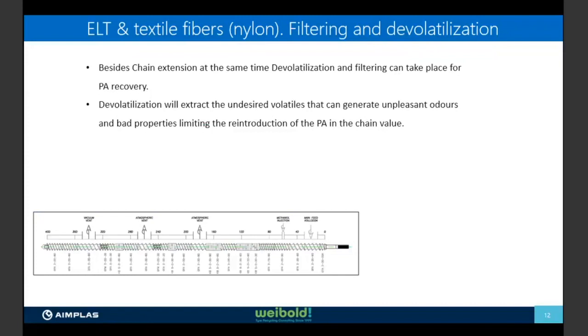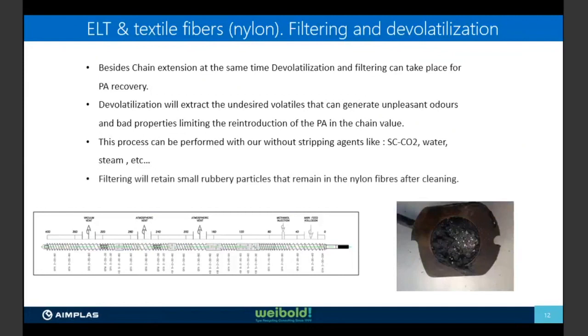So we make the material pass through the extruder. Here you can see the extruder, and here you can see different venting ports. Once the material is melted, we can put those venting ports here. At the same time, we can put vacuum pumps to increase the devolatilization of this polymer. We can also enhance the devolatilization by adding different stripping agents. In this case, it could be supercritical CO2, or water vapor, or depending on the polymer, in this case water will not be so attractive for polyamides. We can add, for example, low boiling point solvents that can act as some kind of scavengers of odor. Then we can remove these unpleasant odors and improve the quality of the polyamide.